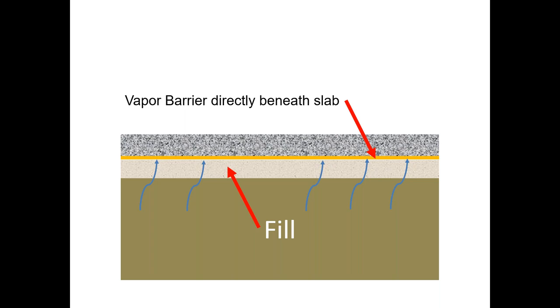Typically what you're seeing there is a couple of different things. One, if you've got a garage where you don't have a controlled environment and the temperatures are dropping below freezing in there, then freeze-thaw will definitely cause that surface to scale. The other thing that happens often when you're dealing with chlorides and brines is the wetting and drying of the chlorides itself in the concrete can be expansive. And over time, that can cause spalling or chipping at the concrete surface.